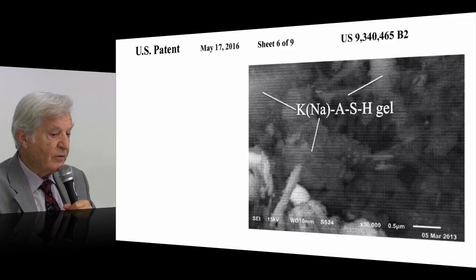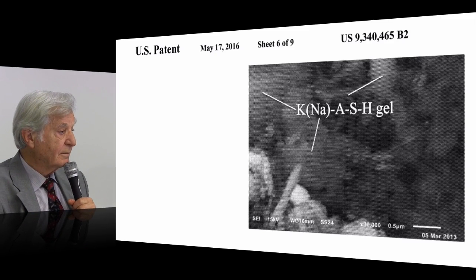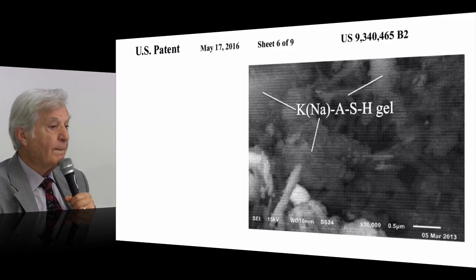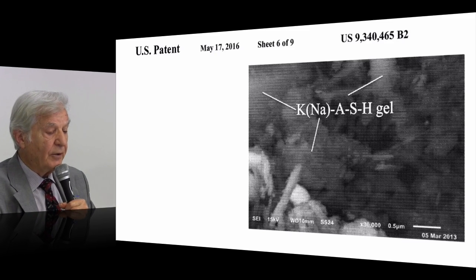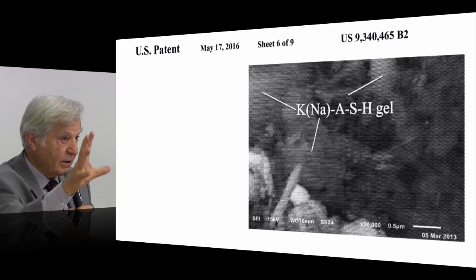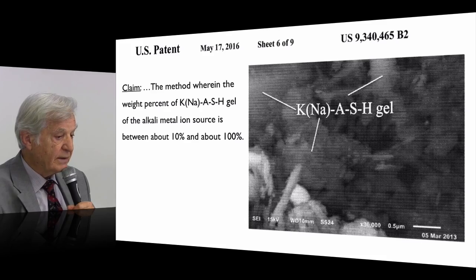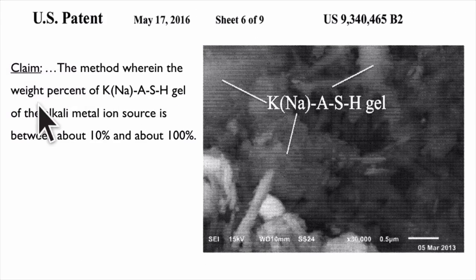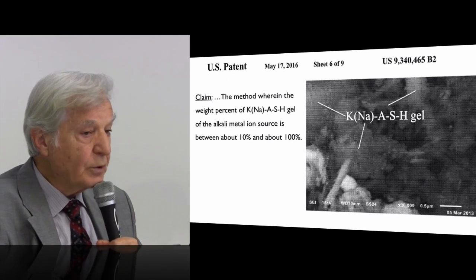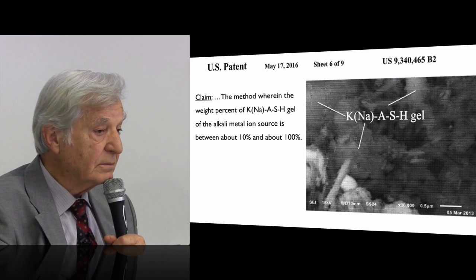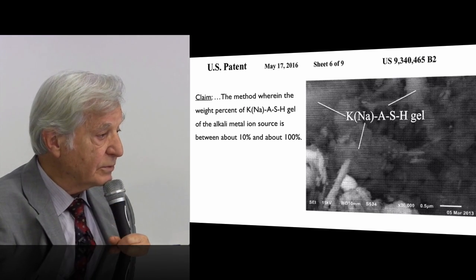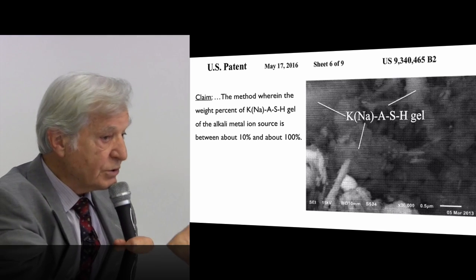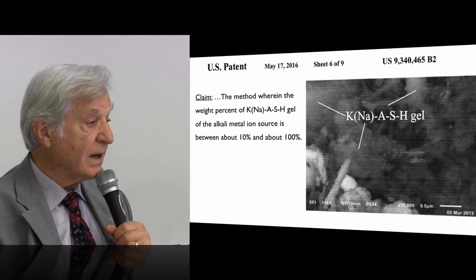What we have here is a K-ASH gel. They are manufacturing a K-ASH gel, but this is their target, and their claim: the method wherein the weight percent of K-ASH gel of the alkali metal ion source is between about 10% and about 100%. For what purpose? To make a fertilizer, to have the potassium cation coming out in earth with water. This is logical to have this type of terminology.